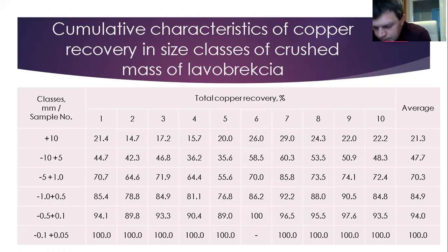Classes from 0.1 millimeters, where recovery is higher than 94%, are well enriched on a concentration table and a corona electrostatic separator.